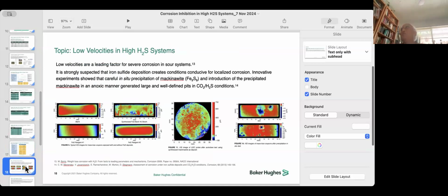Your pipeline should be traveling at a sufficient velocity that small particles are not depositing out. But many times with time, this is tough in the oil field, because you're not able to maintain that velocity because you don't have that production. And you can create heavy deposits, especially in H2S systems. The reason you get the corrosion in these cases is that the iron sulfides are semiconductive, so they create galvanic effects.